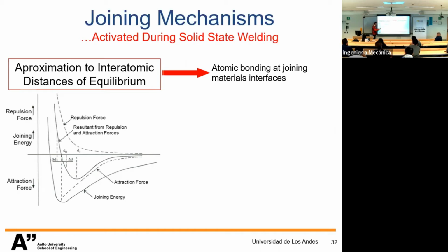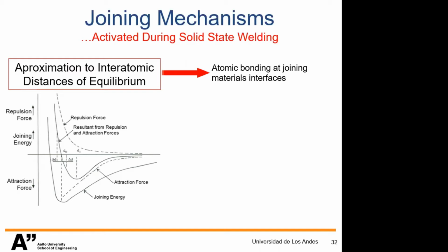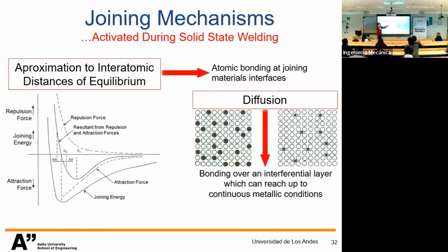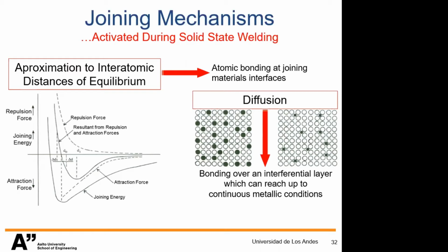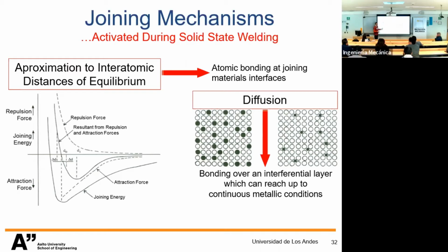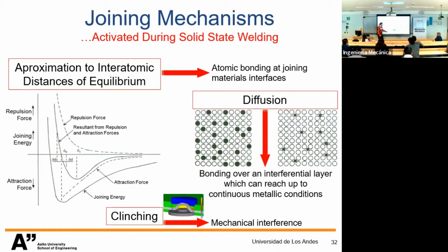This is for low temperature operation, where the distance between the particles is not enough to activate diffusion. We know diffusion from carbon in steel structures, where it's used in general, but diffusion of metallic particles is also possible, also with similar atomic radius. And it just depends on the distance between the particles. So when you have higher temperature for manufacturing, you can activate diffusion, which is strong bonding. When you have low temperature, the distance is not enough to enable the mixture of particles, and so you have atomic bonding. We have also mechanical interference, or what we call clinching, that we take advantage of also.